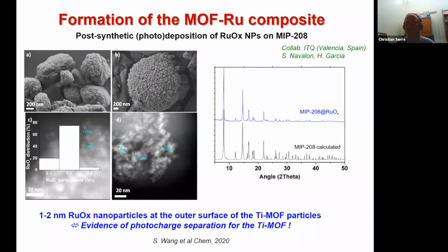And so this material, as it possesses chains, one question was, is it photoactive? One way to do that is to do the so-called photodeposition method, where you have formation of the inorganic nanoparticle where the charge go, the positive or the negative charge. So what they did is they did that with a reduction of ruthenium salt, and they evidenced that very small nanoparticles of less than 2 nanometers were formed at the surface of the MOF. And for them, it was a clear evidence that there was some photocharge separation in this MOF under irradiation. This is why they could deposit this small nanoparticle at specific places of the MOF particle.